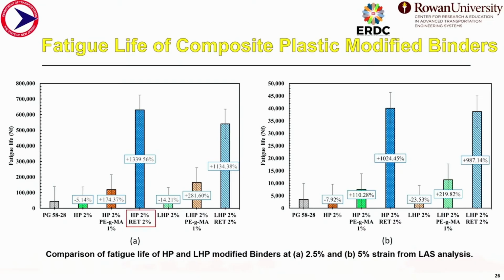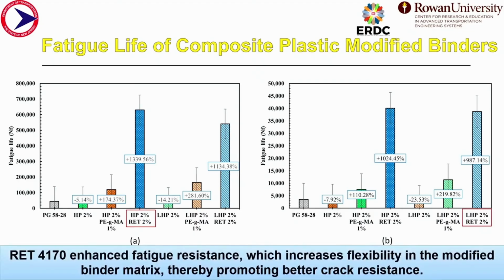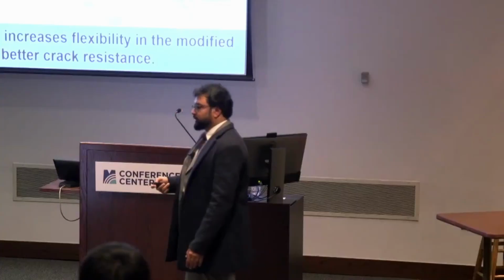So at 2.5% strain, the HP plastic with RET performed pretty well. However, at the higher strain of 5%, we can see the trend of reducing fatigue life, but the LHP and RET has less reduction in terms of fatigue life with the RET combination. So from here, we can conclude that RET is enhancing the fatigue resistance, which increases the flexibility in the modified binder matrix, thereby promoting better crack resistance.